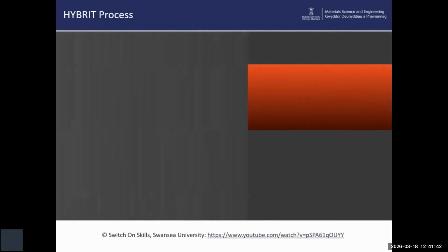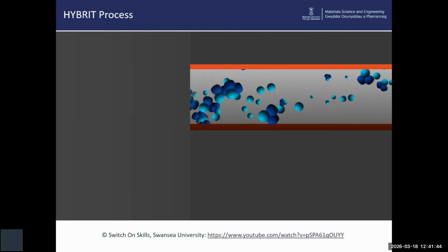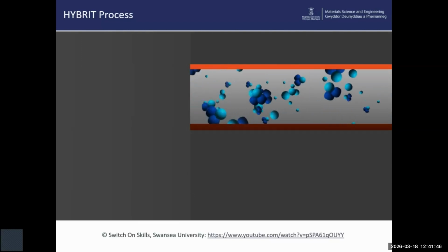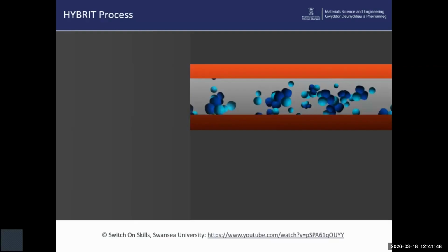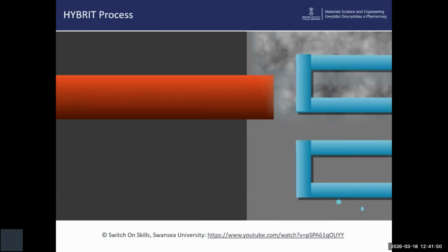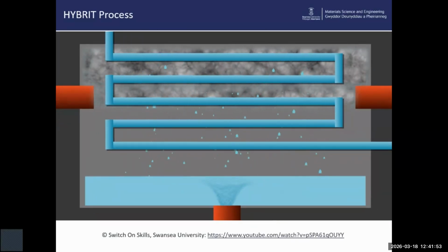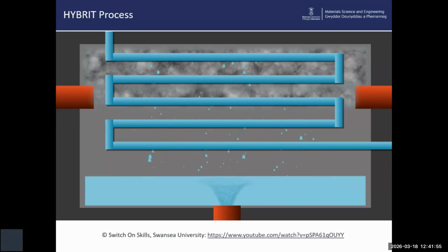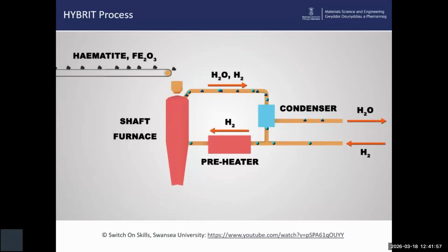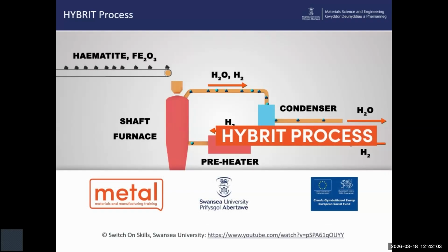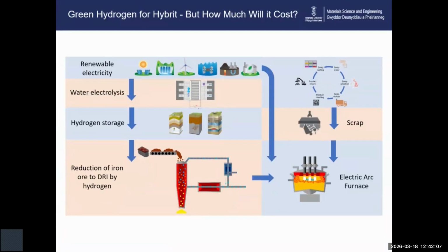The flue gases from the process are simply water vapour, H2O, as a byproduct of iron ore reduction by hydrogen, in addition to unreacted hydrogen. The water vapour is condensed and exits the system, while the unreacted hydrogen is mixed with fresh hydrogen and recycled to the preheater and back into the shaft furnace. A brilliant circular process.